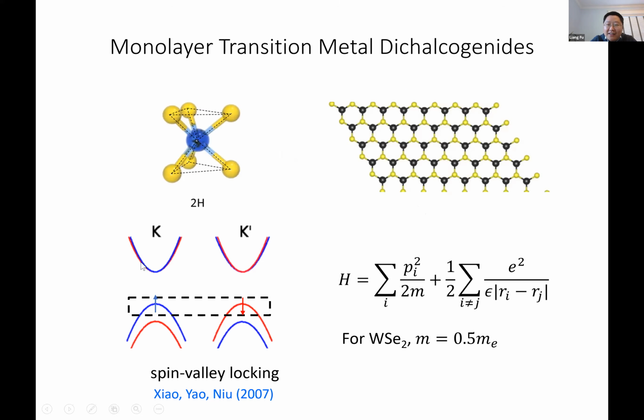One of the key features is that the valence band has a strong spin splitting due to the spin-orbit interaction. In particular, the topmost valence bands are located at the corners of the Brillouin zone, the K and K prime points. Within each valley, the spin is fully polarized out of the plane, and the two valleys have opposite spin polarization. This is a phenomenon known as spin-valley locking. And this is what the structure looks like.